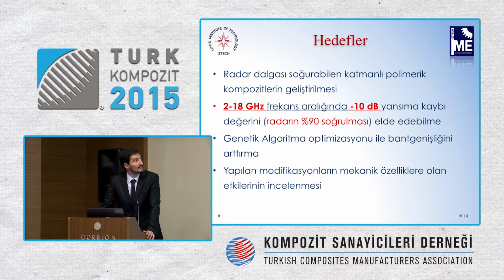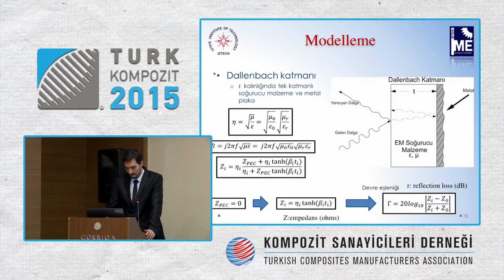Our targets, as I said before, our aim is to create layered polymeric composites which can absorb the radar wave. 2 to 18 gigahertz has been picked as the frequency interval, while in literature 8 to 12 or 4 to 8 have been picked with a single band. They are working on a single band, but here we have a wider interval as a target. 10 decibel reflection loss is aimed, and 90% of absorption is required for that. The genetic algorithm optimization is done. Well, it's one of the targets actually, and the modifications conducted, how will they impact the mechanical properties? We want to detect that.